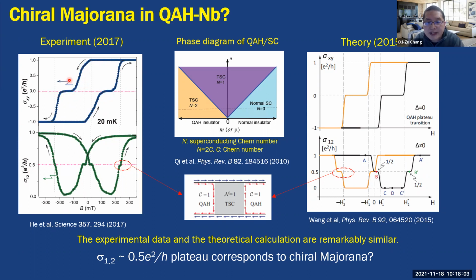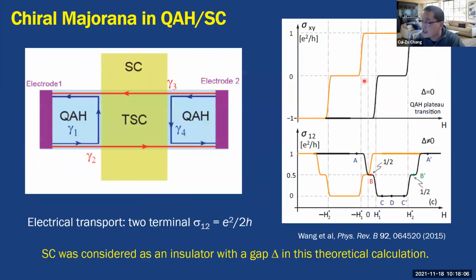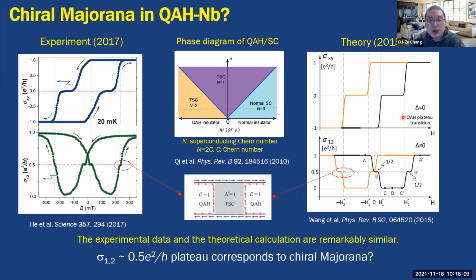Let's compare the experimental result. This is the experimental result, and this is the theoretical prediction. Let's compare these two results. Here is just N equals 2. Here let's define a superconducting Chern number, just the Chern number I defined previously. Two times the Chern number we call n. Here is the n equals 2 regime, here is the n equals 2 regime, and here is the n equals 0 regime. When you tune the magnetic field, it will definitely pass through the n equals 1 regime. This is just the chiral Majorana.